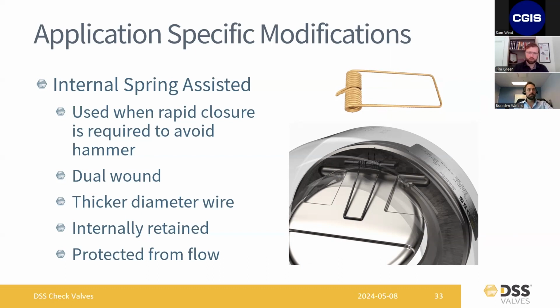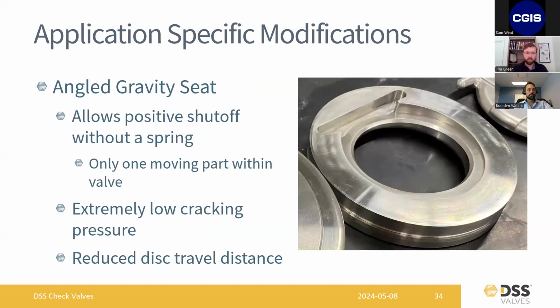So a lot of times what customers will do is get rid of the spring altogether and use our tilted seat. So you can see in this image here, the seat is actually machined on an angle, and that allows you to put the valve in a horizontal flow orientation, and it allows the downward force of gravity to pull the disc positively back into the seat and provide shutoff. So get rid of the spring, use a tilted seat. You've also reduced the cracking pressure. The cracking pressure on these is extremely low. It's less than 1/4 of a PSI. So they open under very low pressure, they close, they don't have as far to swing. It's just a really good design element that leads to a very robust valve that can last for a long time.